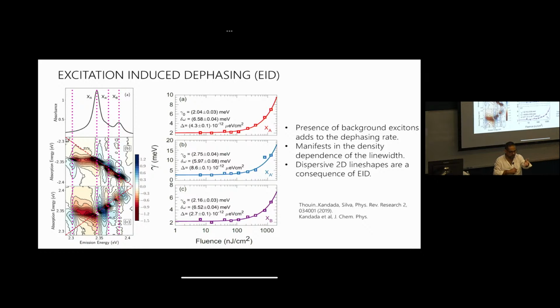That will be very important for the formation of the Bose-Einstein condensates, for example. And so you've got differences in factor of 100 to 1,000 of the scattering rates, but the scattering rates for exciton A and exciton B are not the same, which is the one that is going to feed your condensate. That's going to be a very relevant question. And so how should Victoria design her microcavity to optimize XA or XB, right? And so that's important.